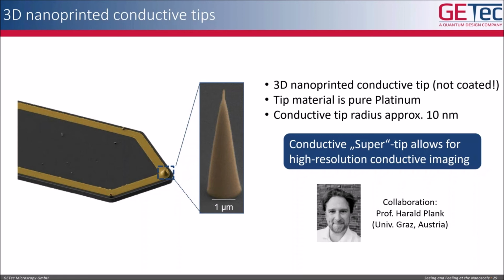We use a different approach: a very unique 3D nanoprinting technique to create our tips. This tip is not coated, it's really 3D printed and made out of pure platinum. We can create 3D structures and add this high aspect ratio platinum tip, which enables us to get to a tip radius of around 10 nanometers. This gives us what we call conductive super tips that allow for high resolution conductive imaging.